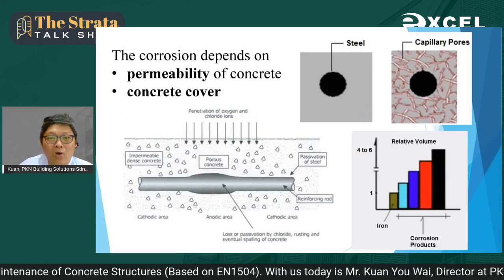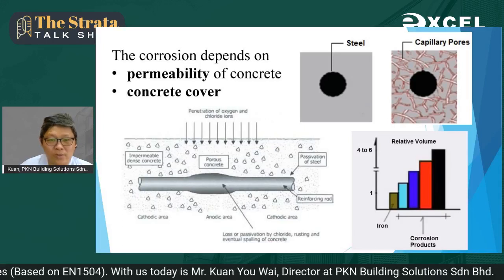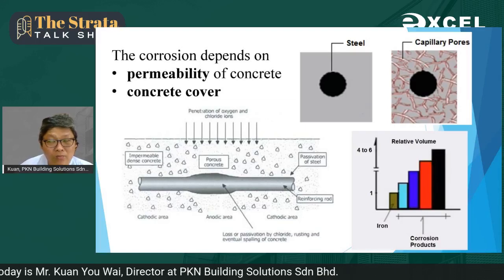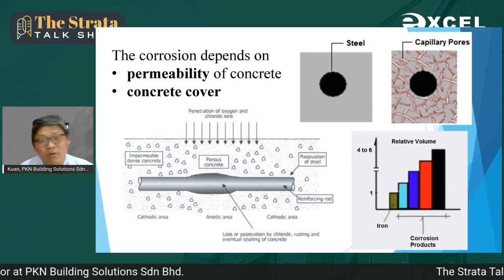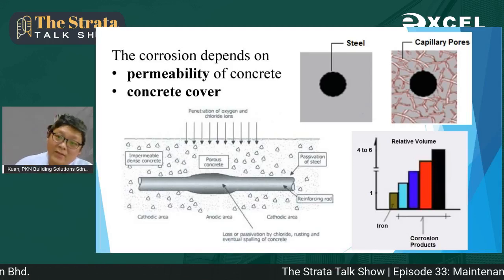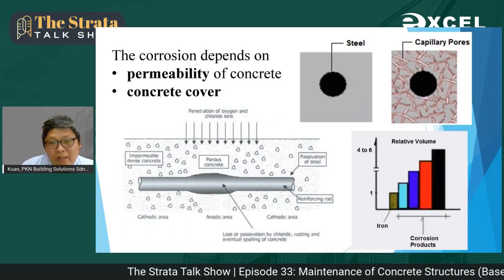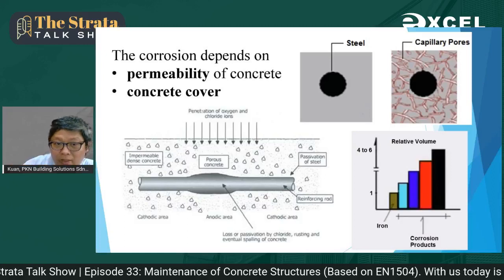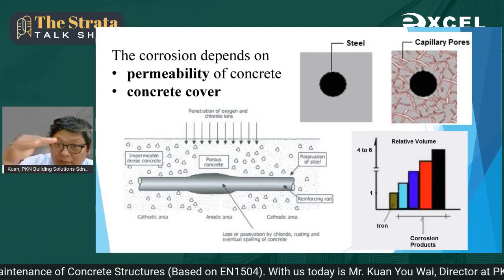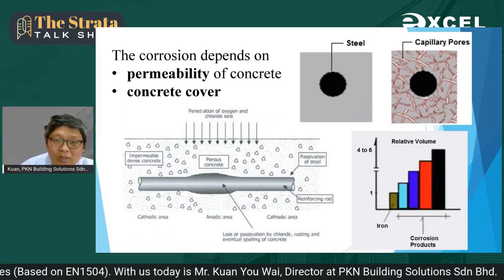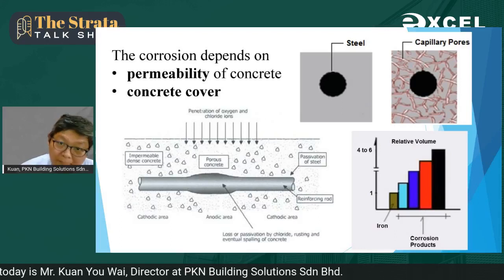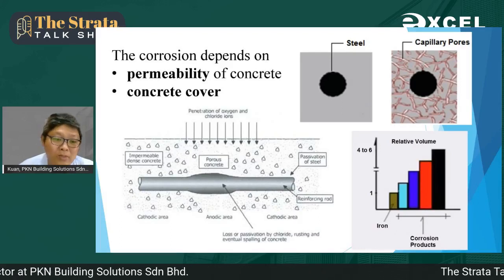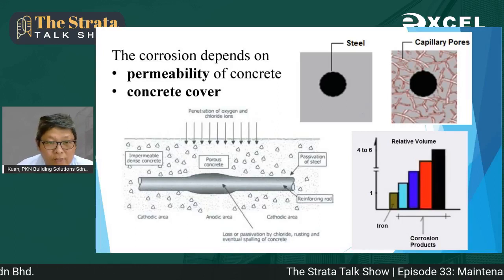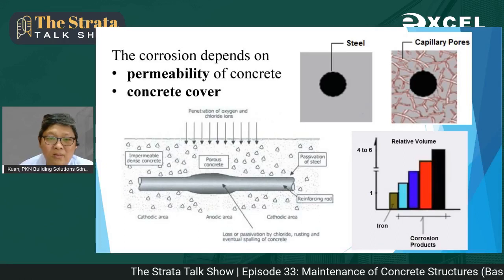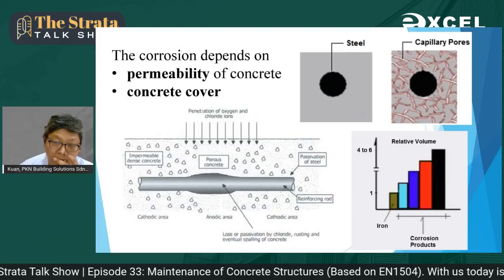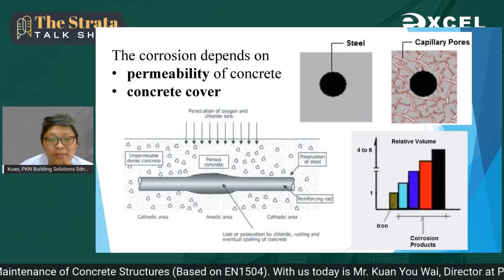How fast the corrosion can start really depends on how impermeable your concrete is, the porosity of your concrete. Of course, the more porous it is, the faster water can travel. And then that makes the concrete cover matter. The concrete cover is the distance between the reinforcement steel bar and the surface of concrete. The thicker the concrete cover, the more durable it is, because it will take longer for chloride to go through. In marine environments or in swimming pools, we need to add additive to make the concrete more solid and dense. So these are special requirements for this type of structure exposed to chlorinated water.